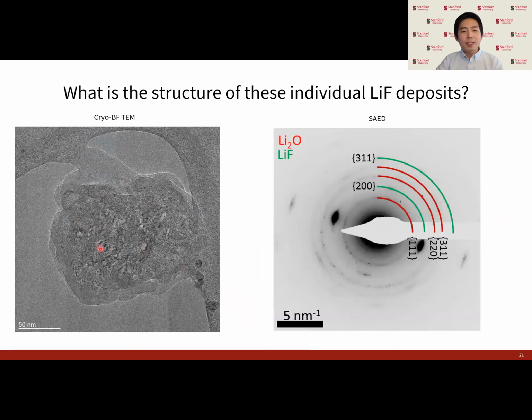Looking at this in bright field TEM, we can see that out here is this outer, more soft organic material. And looking at the electron diffraction, we can further confirm that these are lithium fluoride particles. And it is polycrystalline, although there is a heavy preference for a preferred orientation, along with more random orientations of lithium oxides as well, which matches what we see in the STEM EELS.